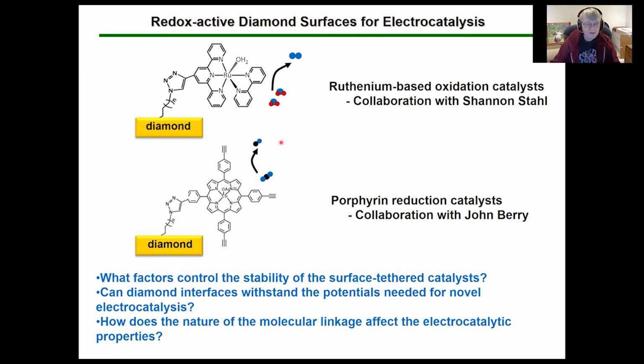So there are a couple of questions here. One is, well, in the grafting that I showed you, we typically have a relatively long molecule tethering whatever is that active group onto the surface. And there's a few reasons why that's helpful. One is the vapor pressure is simply lower, so the material doesn't evaporate. One is that those more hydrophobic molecules generally tend to have lower amounts of water impurities or other things. And in fact, water impurities can be a problem in this.